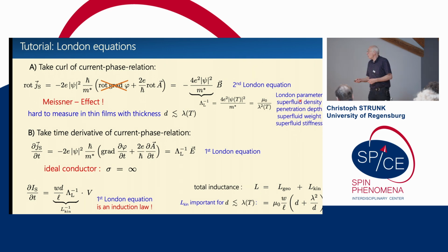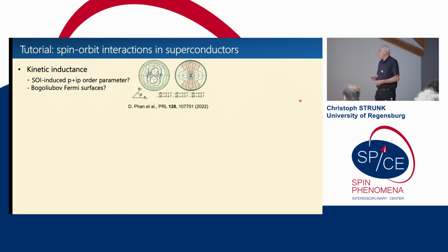Okay, so this motivates why I'm interested in inductance as a quantity to observe. Now, let me give you some examples where this actually has been used, in fact, in materials which are very similar to ours. So I will talk about it, but this is aluminum films on indium arsenide, where the intimate epitaxial interface between the two infects, so to speak, the superconductor with spin-orbit interaction, while the superconductor infects the indium arsenide with superconductivity.